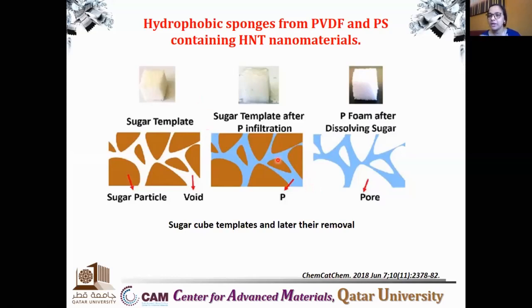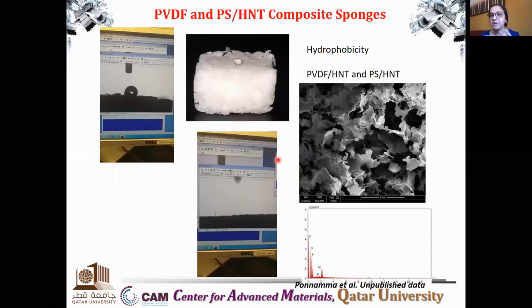So we normally do the sugar template method by dipping the sugar in some polymeric medium, then drying the sugar, and then keeping the sugar in water. What will happen? The sugar will be dissolved in water, leaving the polymer in the form of some sponge. We adopted this strategy because the foams may have different kinds of pores inside, and we found that the water molecules are standing on the top of the sponge.